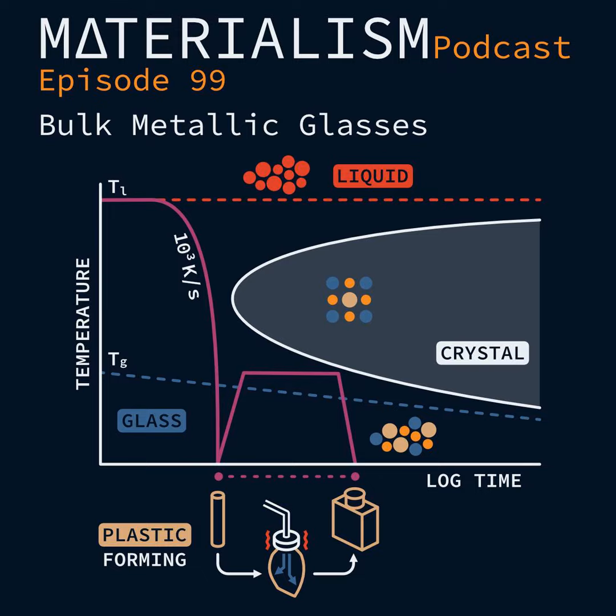One of the things I thought was really cool about this when I was learning about it is, I'd always learned about the TTT diagrams, and I never actually knew how they made them. I sort of figured it was trial and error, like, well, we tried it at this rate, and we didn't see whatever phase form. But here they talk about a really cool way where they've got this levitating furnace, and you've got a pyrometer measuring it. Essentially when the secondary phase forms, there's an enthalpic change that causes the material to heat up. So by monitoring the temperature as a function of time with the pyrometer, you can actually see the onset of crystallization. And from that, you can construct the TTT diagrams, which, for somebody like me who never knew where they came from, is a way you can actually measure it pretty accurately.